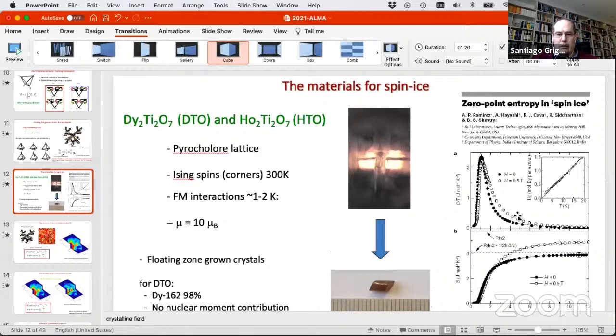So the work by Ramirez here, this measurement where they determined the residual entropy, was done on polycrystalline samples. And so essentially the answer is, it's nice to have single crystals, but it's not necessary. And maybe the other thing I should say, it's something which is unusual for this type of materials, it's not too difficult to grow single crystals of these materials. In some other cases, it's a real nightmare to get a good quality single crystal.